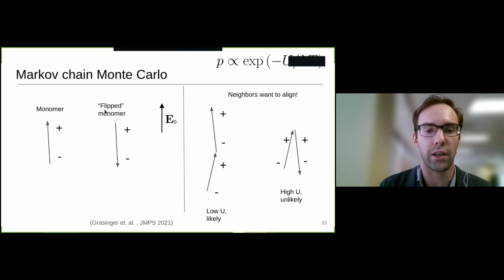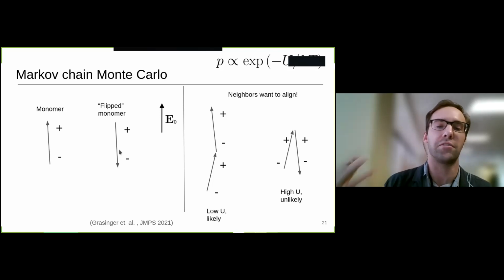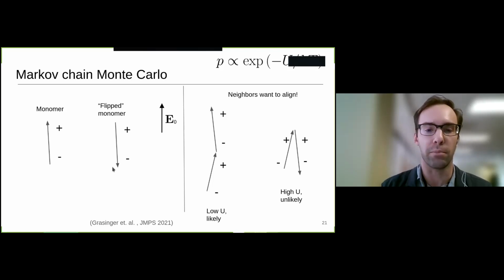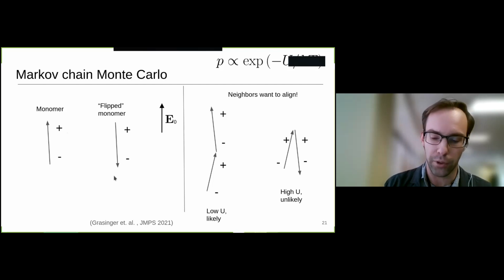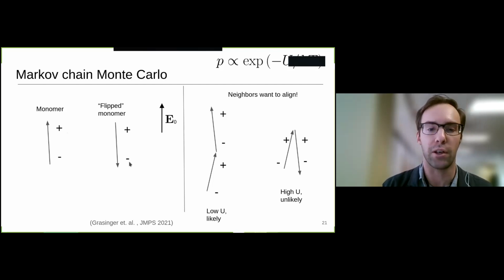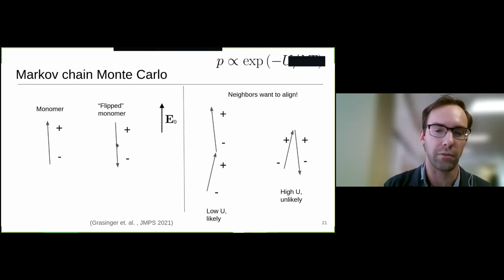What we find with the dielectric monomers in particular is that if we have a monomer aligned with the electric field and a monomer in the opposite direction of the electric field, these have a very similar energy. But there is an energy barrier between them. So being aligned with the electric field or in the opposite direction, both have a high probability of occurring because they're low energy states, but it's very unlikely to have some sort of intermediate state. And so we might think, well, okay, if we want to generate our next random sample, one thing we can do is start randomly flipping monomers such that they're in the opposite direction, or reflect the monomer directions in the plane orthogonal to the electric field, something of that nature.